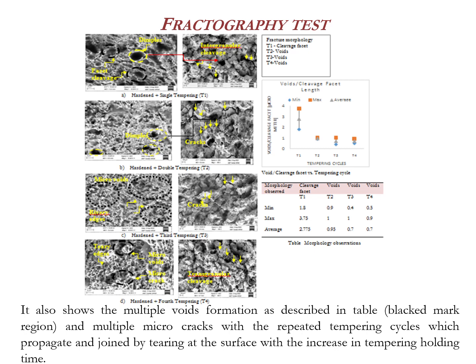Fractography test. Fractography images indicate that from single to 4 times tempering condition, the brittle failure indicated by cleavage facet in single tempering shifted to ductile failure as indicated by multiple voids and teary edges in 4 times tempering condition.